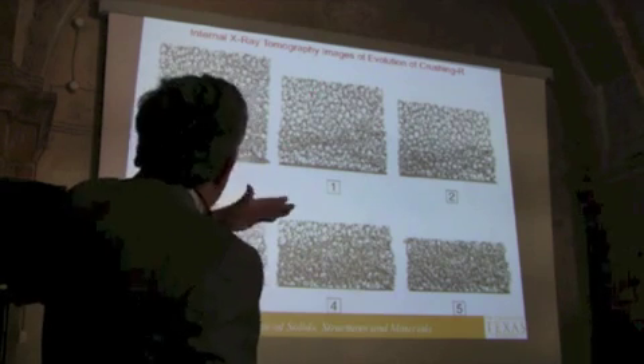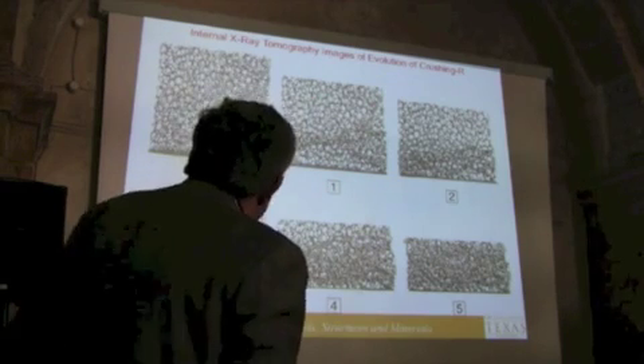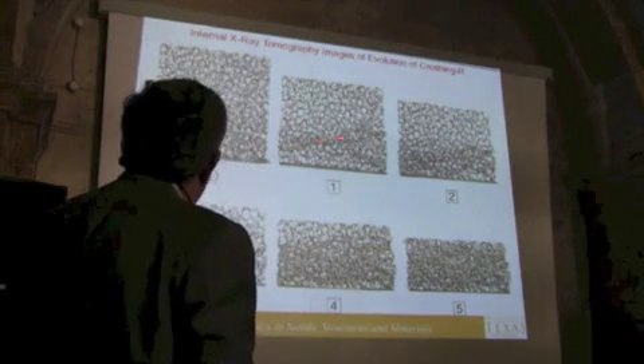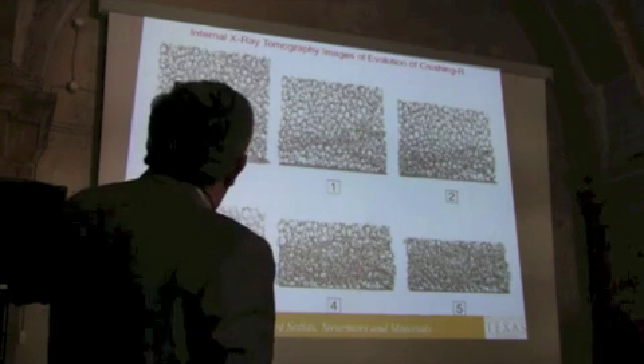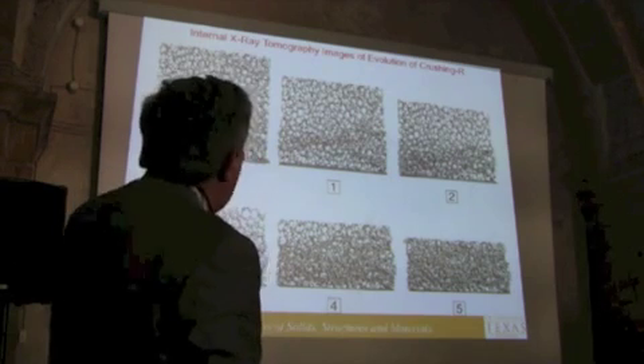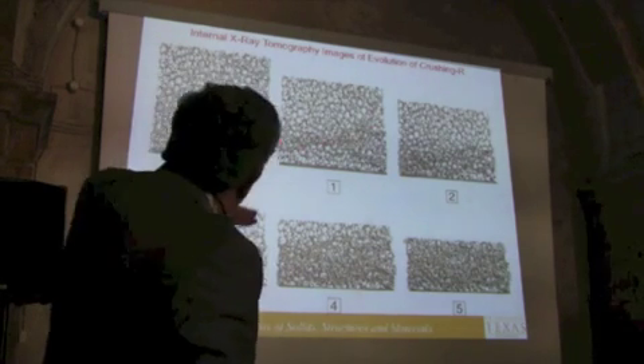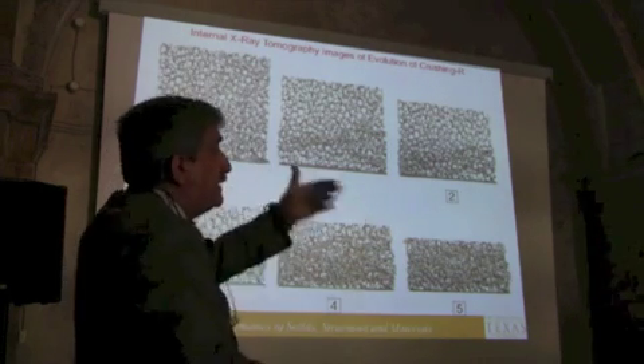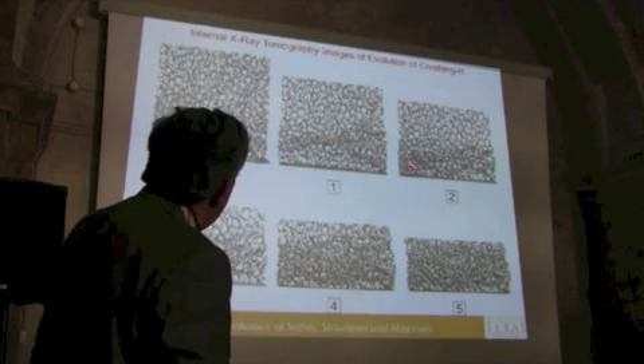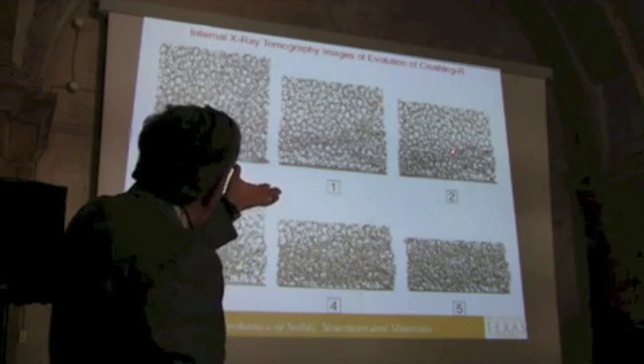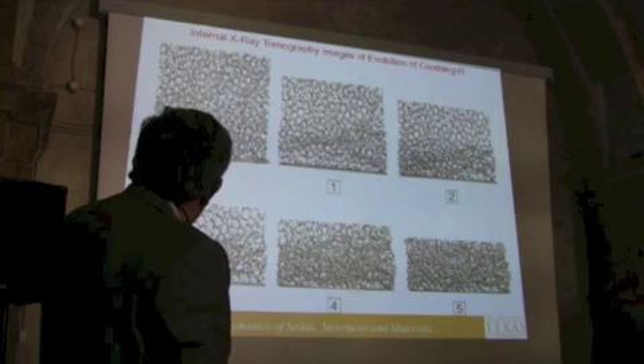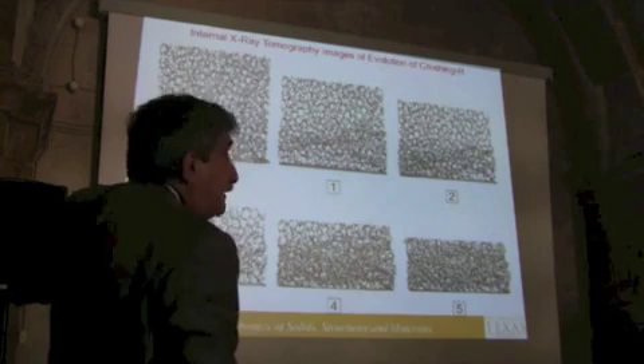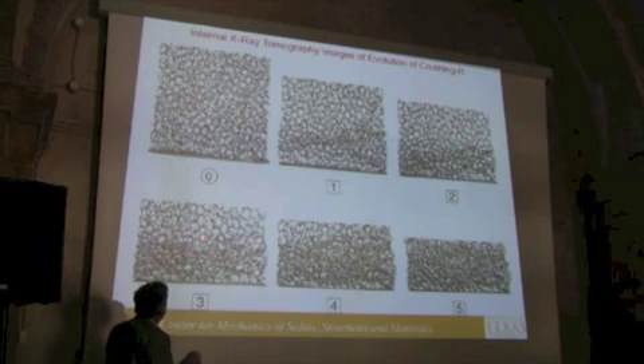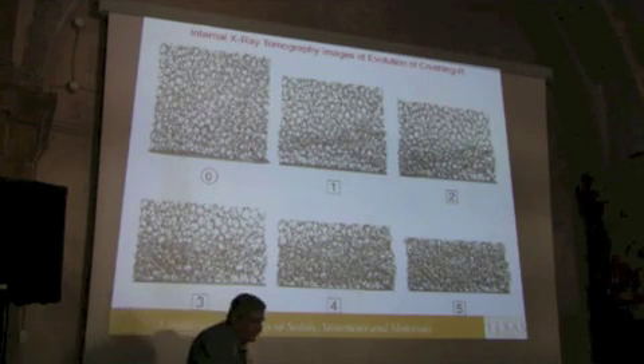Now, where it starts first, there is no preferred orientation. If anybody is looking for any special inclinations, it occurs where there is the biggest weakness. It's a random foam, so there are weaker spots, and the profile of these bands is 3D through the specimen. As we continue loading, more cells crush, and then gradually the crushing zone moves upwards in this case. It could be downwards in another case. But I notice again that what we have is uncrushed material and crushed material. This is the characteristic of propagating instabilities.